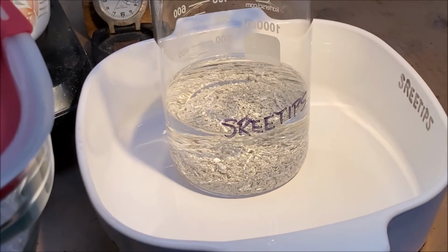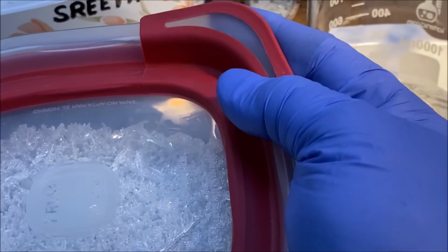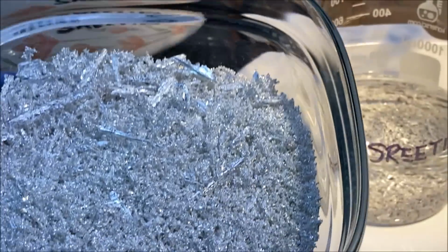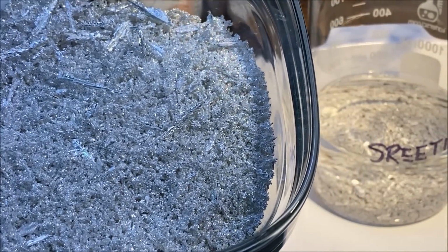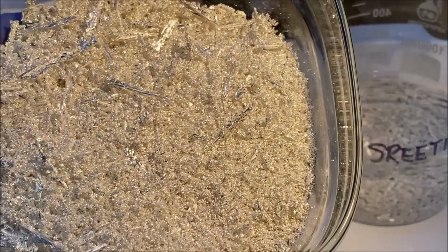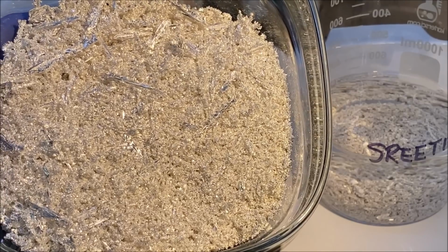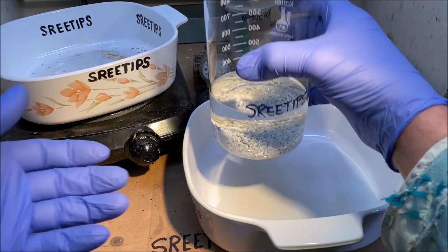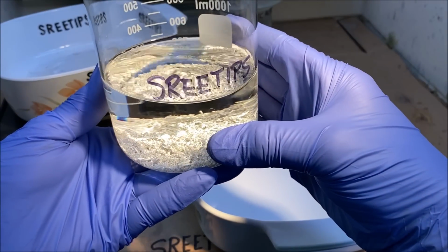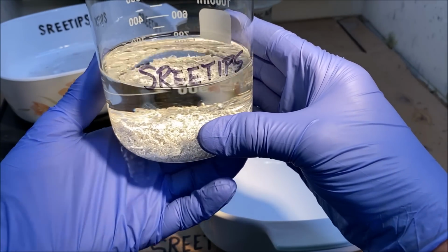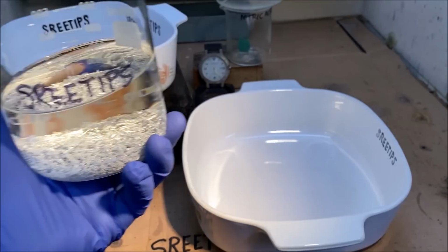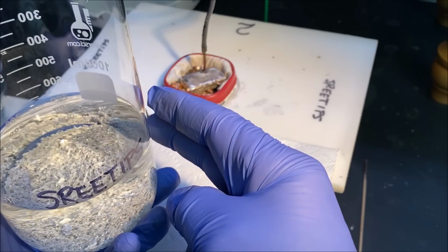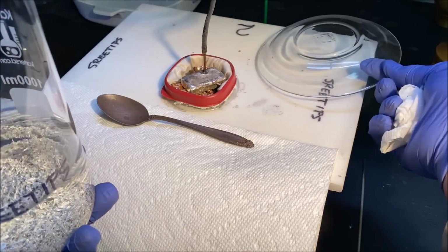You can tell by the color of that solution that this silver is going to be ultra high purity, probably very close to 5 nines fine pure silver crystal. It's been allowed to cool down. It's cool to the touch now. We're going to take it over and add some of this electrolyte to our silver cell. I'm going to pour this right on in. I don't think there's any need to filter it. There's nothing in it at all.